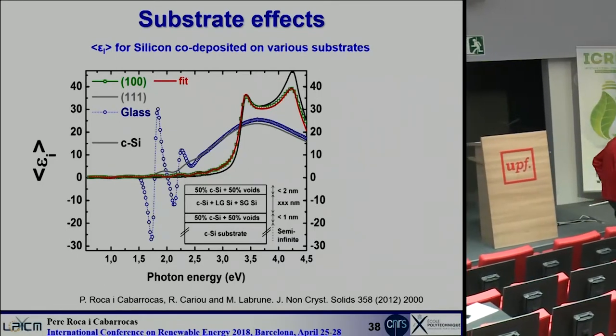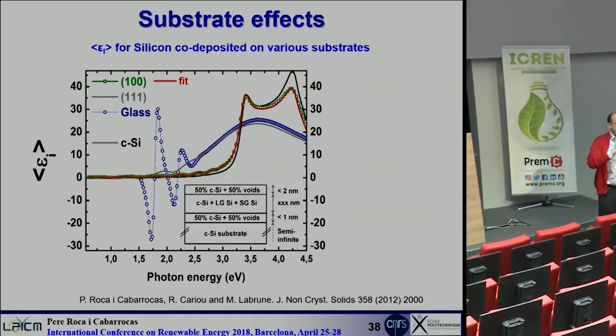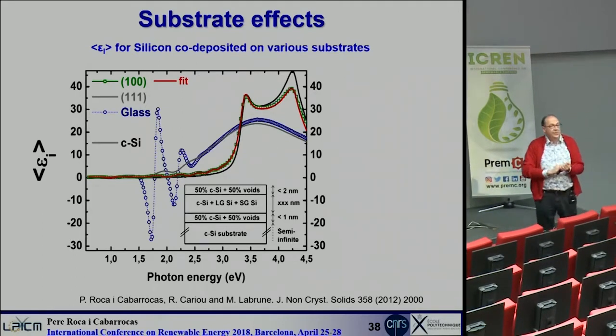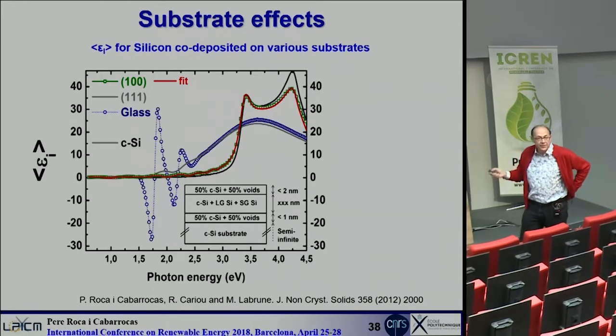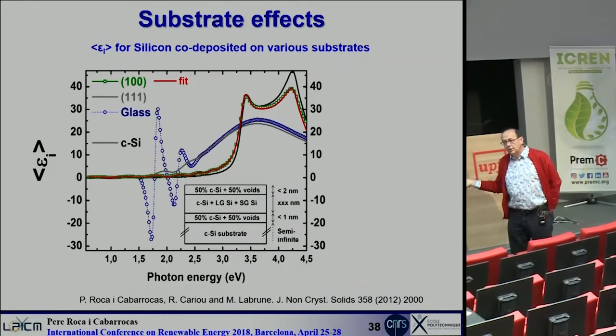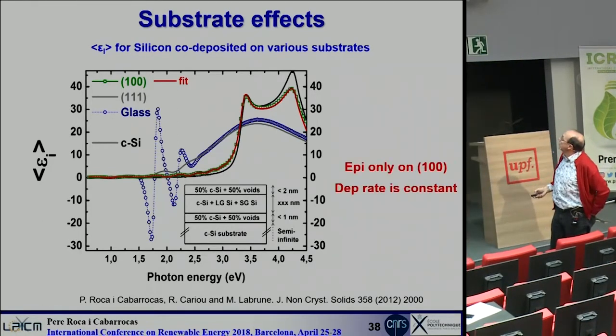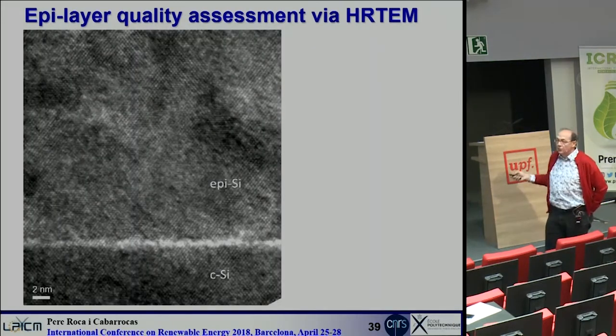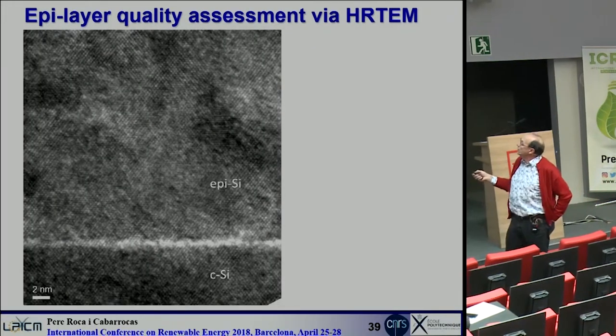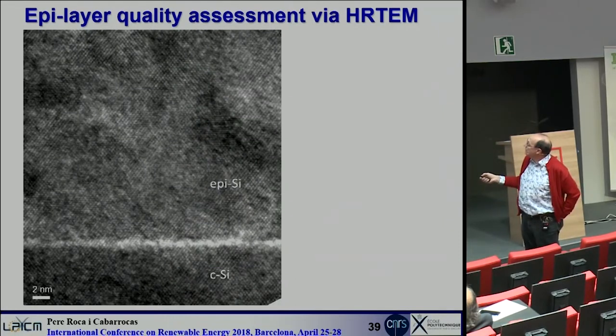So even if you don't know ellipsometry or optics, if you get the same fingerprint, the same characteristics, it means that what I am growing here is crystalline silicon. And if you are not specialized in ellipsometry, doesn't matter. We can do TEM, you go to the TEM, you have the epitaxial layer, 2 nanometers, crystalline silicon, epi layer.